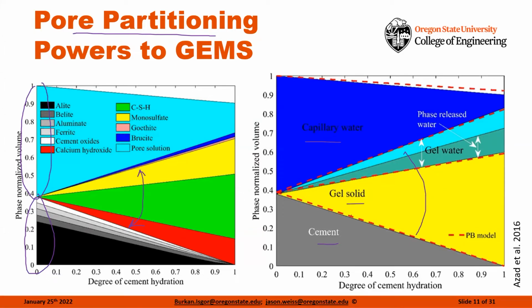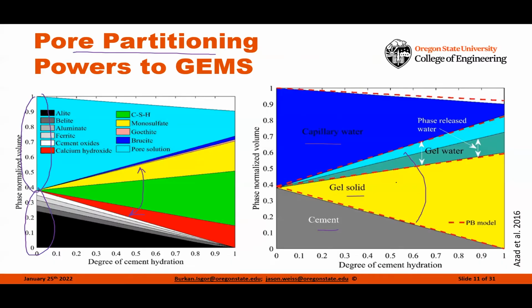And if we overlay our products here, and we go through and identify these and distribute them in the pore partitioning model, we can see that there's a relation between the Powers model, which is shown in the colors in the back, and the red lines, which is the thermodynamic model that we're showing here. So the real benefit here is we can actually link thermodynamics with a lot of the models that have been used over the history of time, using this pore partitioning concept.